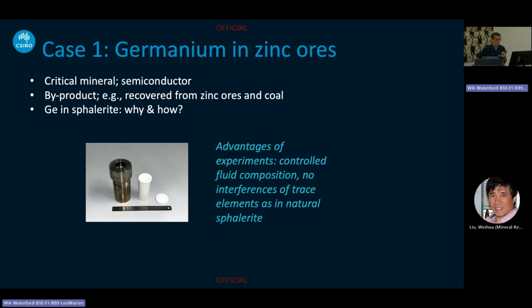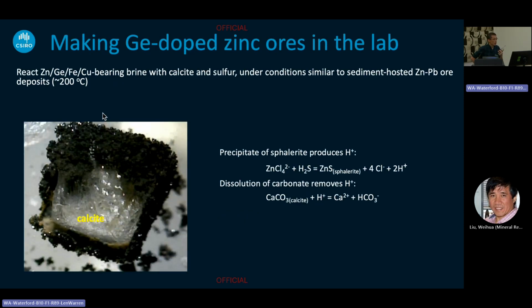We will have some hypotheses of ore forming processes, and then we can simulate and test our ideas. So the first step is to try to make this germanium-rich sphalerite ore in the lab. What we did is we reacted a germanium, iron, and copper bearing brine, similar to what we observe in those MVT or Irish-type deposit systems, and reacted this fluid with calcite, the carbonates we see in those systems.